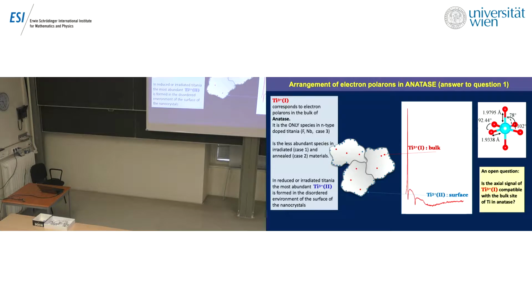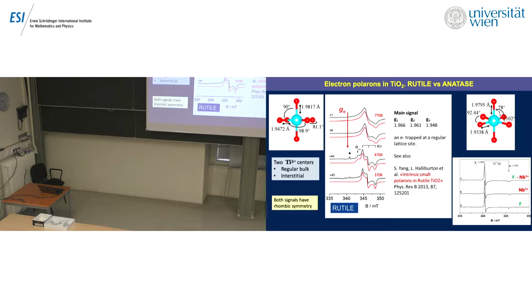So is this axial signal compatible with the bulk site? Unless, if you trap an electron, you become a polaron and suddenly become very symmetric, which is quite improbable, there is something that must be explained. So we try to explain by comparison with the case of rutile. Rutile is much more symmetric, less asymmetric than the symmetry of the titanium ion in anatase. Nevertheless, we have a rhombic system with 3 components and not an axial system like in this case.